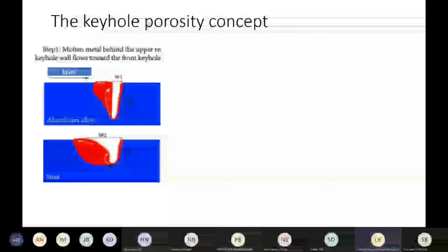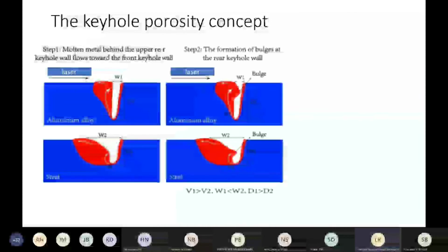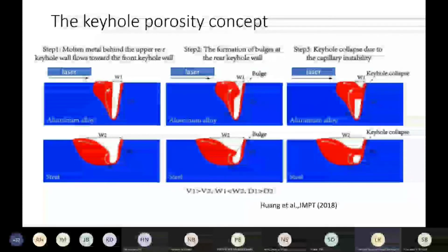So how keyhole porosity forms is the basis of how we are going to eliminate it. So how do we understand it? We look at a molten melt pool. See that at a very high aspect ratio, and when the laser is scanning, let's say, left to right, the back end of the pool starts bulging out, and then it goes towards the front end of the pool, and finally, due to capillary forces or capillary instability, this keyhole collapses. And then you have the entrapment of a pore. That is how keyhole porosity essentially forms. And this is shown in two different metals. One is your aluminum alloy and one is your steel.